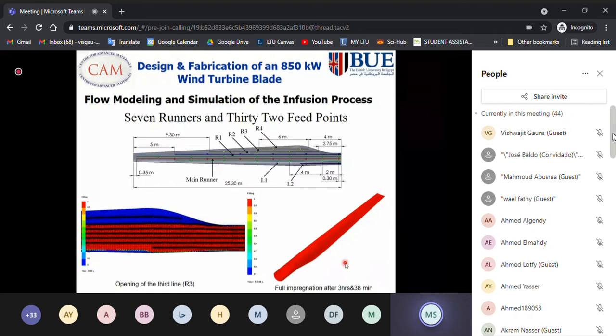Now we have to be careful because of the pot life of the resin. Once you mix the two components of the epoxy, you have 1 or 2 hours before they go into full curing. Also, you have to remember we're mixing large amounts, so the amount of exotherm coming from the mixing process is quite high, and in this case the curing process will be accelerated. So I had to make sure that the pot life of the mix is larger than this number of hours.